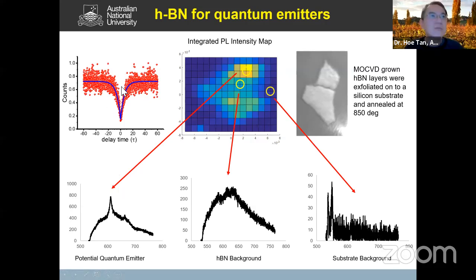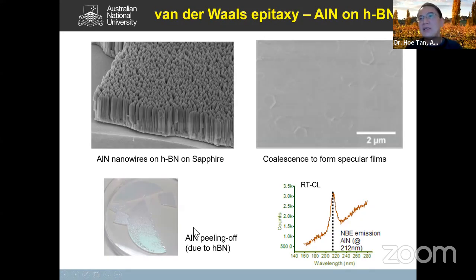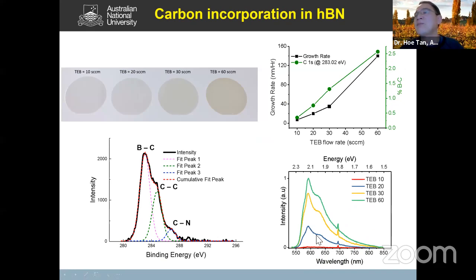And if you do the autocorrelation measurement here, you can see this is a proof that this is a single photon emission. So now, by controlling the amount of defects or carbon impurities inside, we can control the amount of single photon emission, the density of single photon emission.